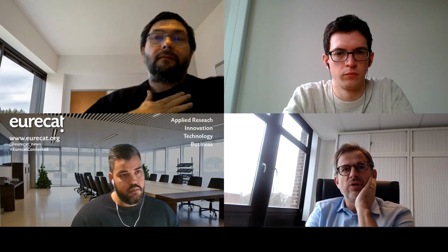Of course there is a bunch of research and study on improving damage models, advanced Gurson model to take into account distribution effects and plastic anisotropy, etc. And also several populations of voids due to carbides on top of the manganese sulfide, etc. So the message for today was more to help thinking about these two contributions and separate them from a more didactic viewpoint. But there is a lot more to do on understanding and modeling better the two terms. That's for sure. You're right.